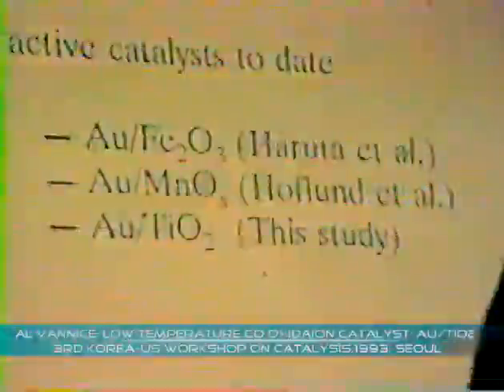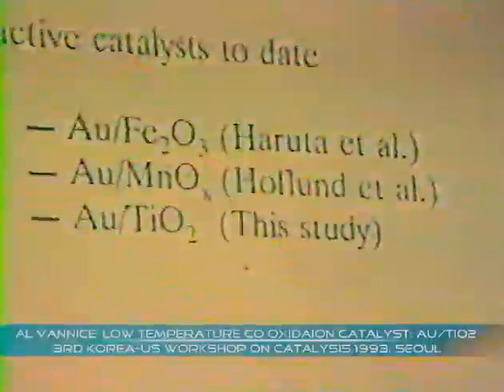Subsequent to that, working with a NASA group, Professor Hoflund at the University of Florida has been conducting work dealing with gold dispersed on manganese oxide, non-stoichiometric manganese oxide. This catalyst system is also very active, more active than platinum on tin oxide, and is also active at temperatures below room temperature.